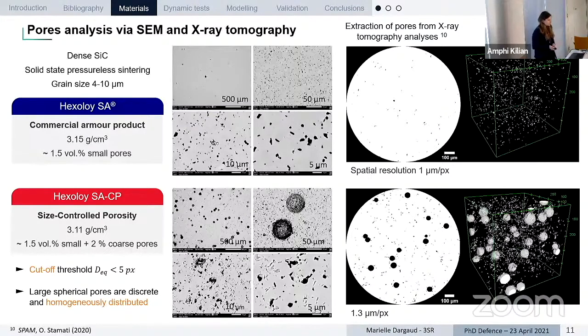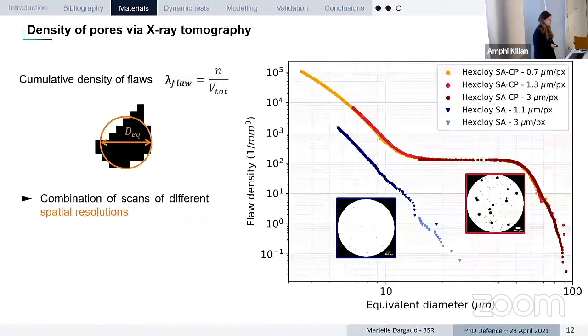Then, from this extraction of pores, we can analyze the distribution of the defects and their size, and we can obtain this plot, where we have the cumulative density of flaws in the material according to the equivalent diameter of a defect, which is taken equal to the equivalent diameter of a sphere of the same volume. Here you can see that we've done several scans at several different resolutions to be able to capture a large range of the different defects in the material and represent properly the defect population.